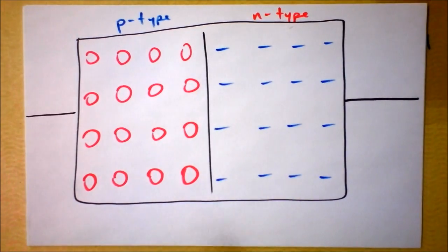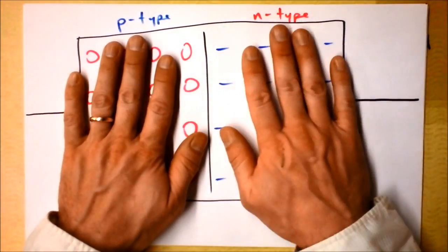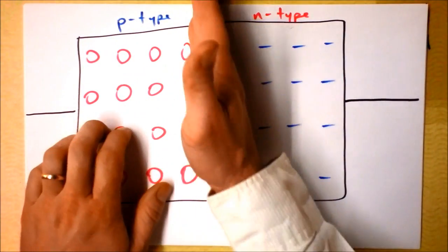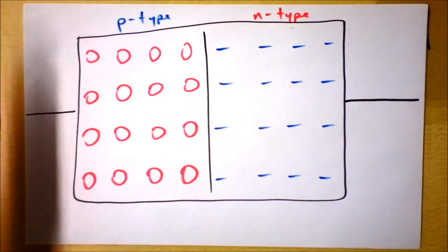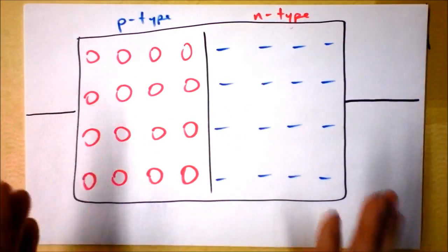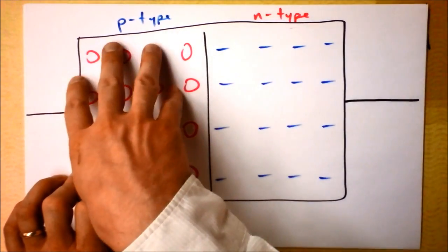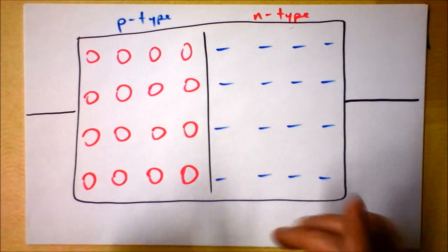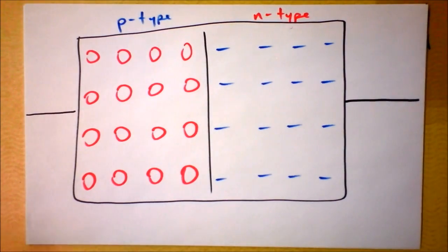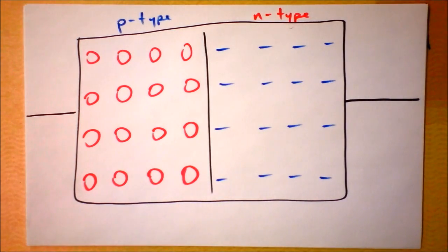And actually, I have to remind you that this is not actually how you would do it. You wouldn't get some P-type, get some N-type, and glue them together, because you're going to have oxidation on the surface, and they're going to be crystalline facets that don't line up. What you really need to do is make a block of silicon that somehow has P-type and N-type transition within it. So it needs to be from a single crystal. And you can do that again with the gun. You can actually shoot it a whole bunch with some really interesting, well, not a light gun in that case, but some radiation.